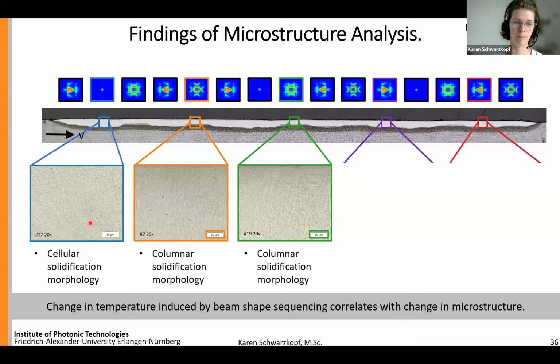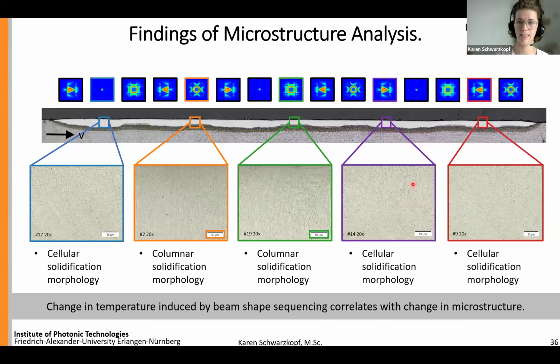And now we would expect to have the triangular beam shapes to be somewhere in between here and here, because here we were measuring the lowest temperature, whereas here we were measuring the highest temperature. And this hypothesis is also confirmed in the optical microscopy images, where we can see also a cellular solidification morphology for the two triangular beam shapes.